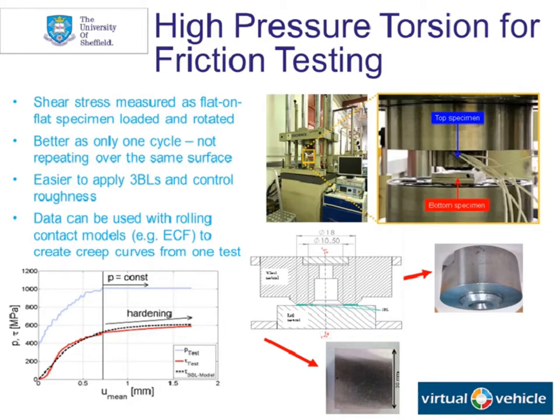This has many advantages. It's a one-cycle test. It means we're not cycling over the same point on the materials a lot. Makes it much easier to apply third body layers and to control roughness, which is very important in assessing friction levels. The data we obtain from the testing can be used with rolling contact models, for example, the enhanced creep force model that has been developed by Virtual Vehicle, but there are others. And we can use the data then to create a creep curve, which is a very important bit of information for assessing what's going on within the contact and how third body layers and applied friction management products perform.